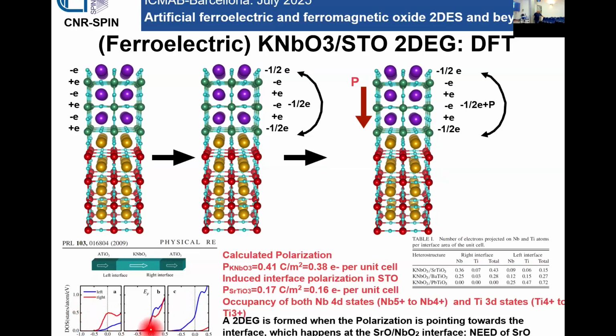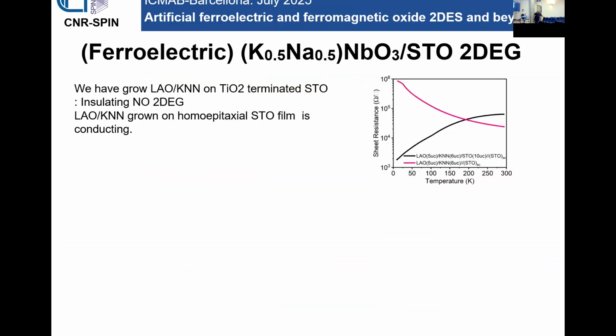And from this calculation, it's practically clear, also from the final table, that only when we have this configuration, essentially, we can have a 2-dimensional electron gas. And from the point of view of minimization of the energy, it seems that the system, when the interface is strontium oxide and niobium oxide, wants to have the polarization down. So these are the theoretical predictions. Now let's see how to realize all this experimentally.